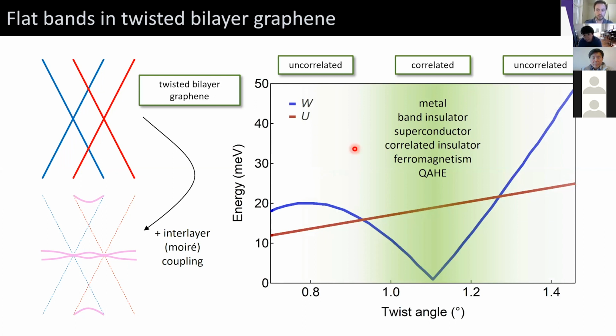And indeed, work from Pablo Jarillo-Herrero's group at MIT in 2018 really sparked a massive new subfield of van der Waals engineering, in which they realized that two monolayer graphene sheets twisted to 1.1 degrees basically give you access to more or less any state that we know about in bulk materials and condensed matter physics. So we can tune between metals, band insulators, superconductors, correlated insulating states. With additional conditions, we can realize ferromagnetism and quantum anomalous Hall effect, really all within a single materials platform, and all tunable just by changing the charge carrier density.